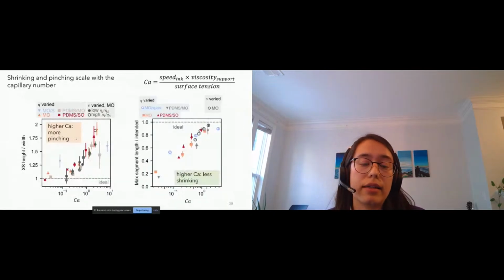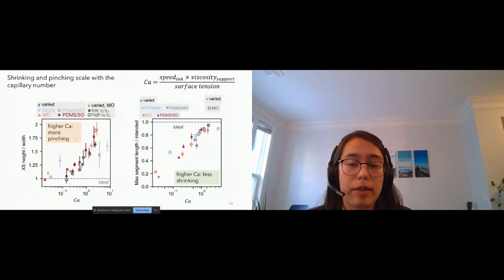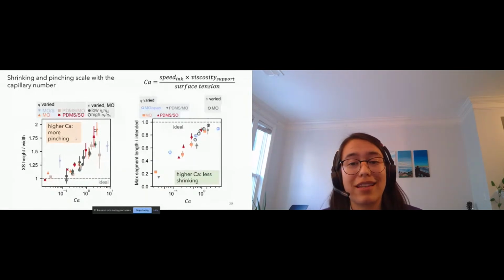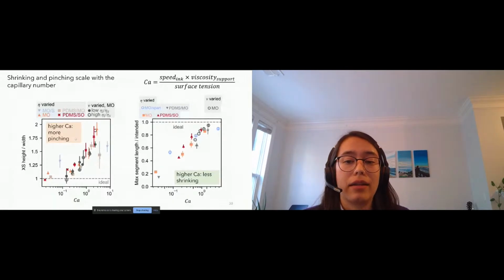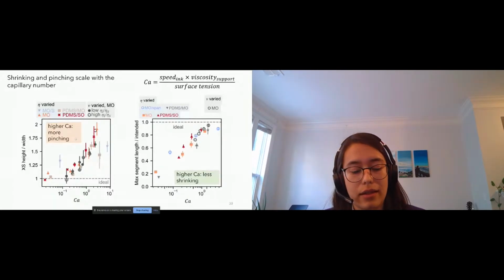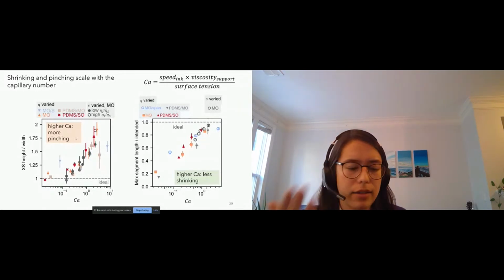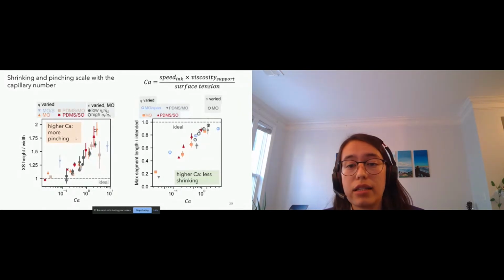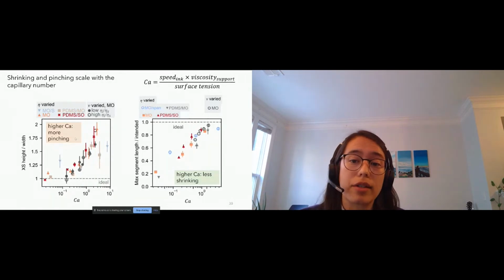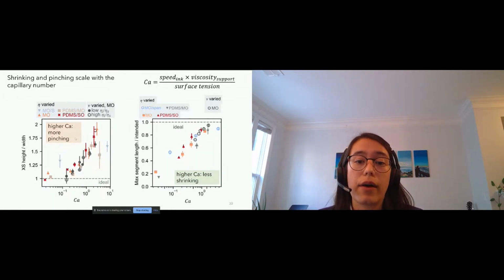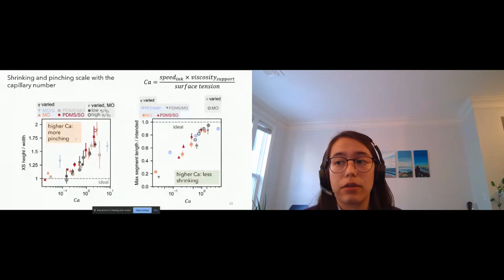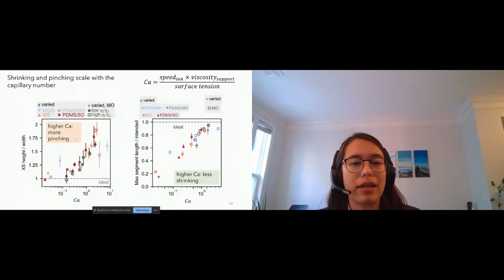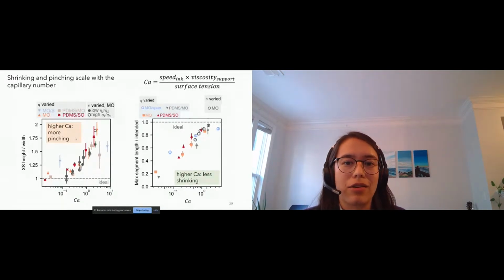If we plot the length of these filaments as a function of capillary number, you can see that we get longer filaments closer to the ideal length as we increase the capillary number. And so in order to suppress that shrinkage that I talked about at low ink viscosities and low support viscosities, we need to use a high capillary number system. So as a trade-off, we'll have to be able to deal with a little bit more pinching and a little bit taller aspect ratios than ideal.